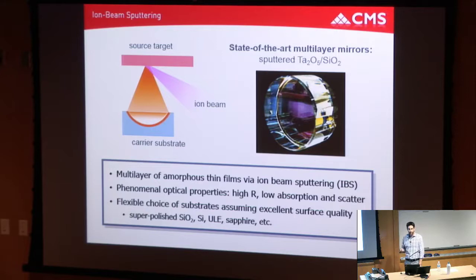Phenomenal optical quality, let's say sub part per million absorption is possible. These are angstrom level RMS roughness, so you know, PPM level scatter. And the beauty of this process is it's very flexible. I can take almost any substrate. It can be structured, it can be curved, it can be made of silicon, sapphire, whatever, and I can directly deposit that coating. As long as I can guarantee good adhesion, and I have good surface quality on that optic, I'm going to get a good coating on that surface. And so this is the state-of-the-art, or sort of gold standard, for optical interference coatings for certain applications,